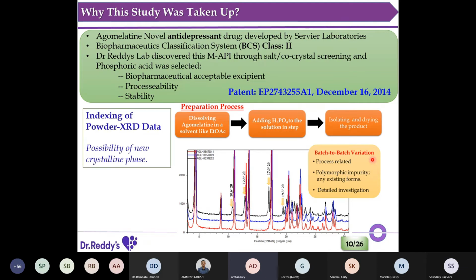What we came to know, using a very simple technique called powder indexing. Powder indexing is a very powerful technique; it can tell about the phase purity of the material. From this we made 100% sure that the extra peaks we are getting in the powder XRD are not from agomelatine polymorphs, because there are three to four different polymorphs existing for agomelatine. So they are not part of the pure agomelatine polymorphs, and there is a possibility of a new crystalline phase. This problem forced us to understand the material in full strength, because we have to have a control strategy to make reproducible batches.